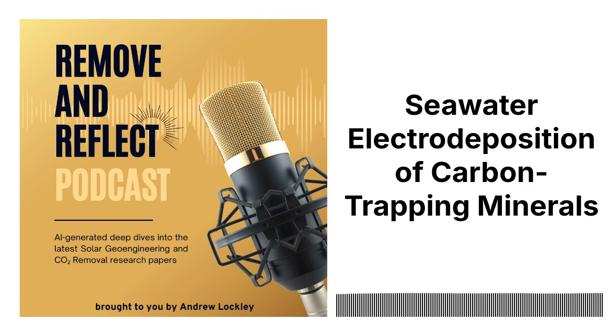Now, why is that porosity beneficial? Well, it's actually quite important because it allows fresh seawater containing those calcium and magnesium ions and dissolved CO2 to continue to reach the reaction sites on the cathode surface, even as the mineral layer thickens. So it's like the pores are creating channels for those reactants to flow through. Exactly. They keep those pathways open. It's a pretty neat self-regulating system. And what size were those pores? They observed pore sizes within the aggregates ranging up to 10 millimeters. Wow, so some of them were quite large. Interesting. And the composition within these larger structures, was it uniform throughout? Interestingly, no, they found that the composition wasn't entirely uniform. Really?